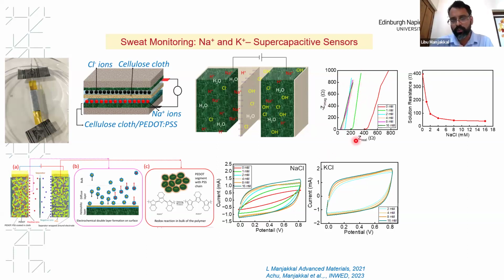And this is due to PEDOT:PSS being a conductive polymer. When reacting with a sodium chloride solution, an electrochemical double layer forms, and also, because PEDOT:PSS is a conjugated polymer, a redox reaction occurs. By using this, the ions are stored on the surface, and depending on the concentration of the sodium chloride or the potassium chloride, the conductivity or the charge storage of the supercapacitor varies.